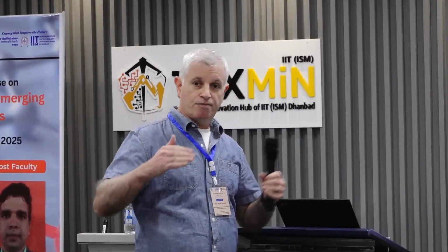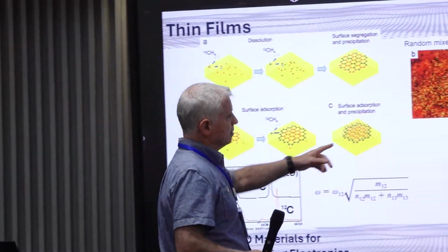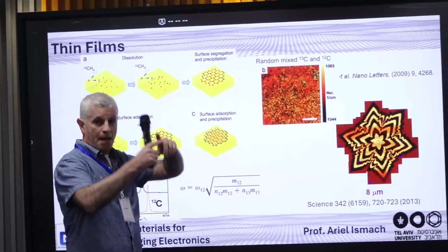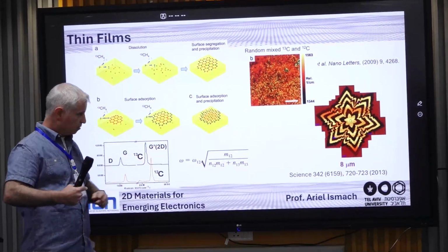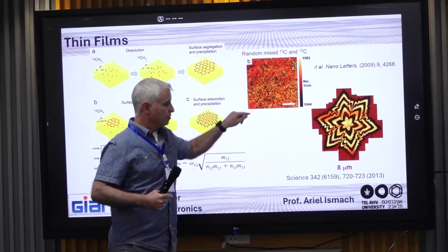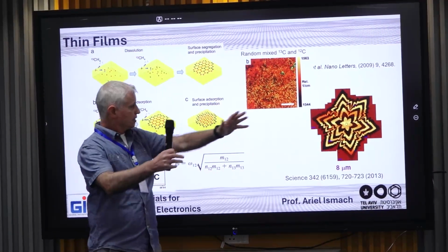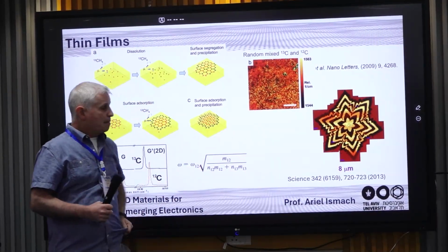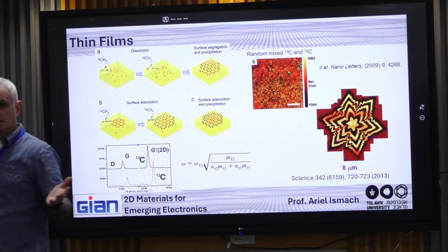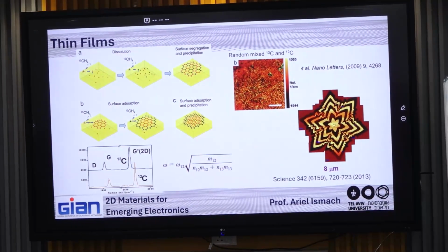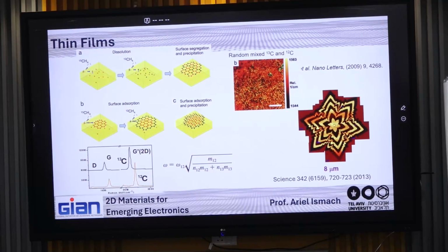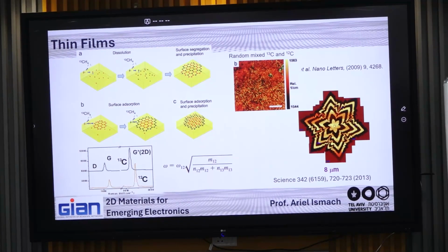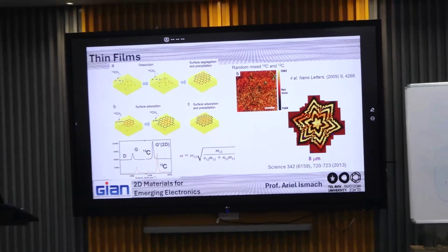They did cycles for each isotope. After doing that on nickel, they did a Raman map. In Raman you can get a picture, a mapping of the specific peaks on the surface. And you see that the map shows a homogeneous mix of the signal from the isotopes, so they couldn't differentiate anything.